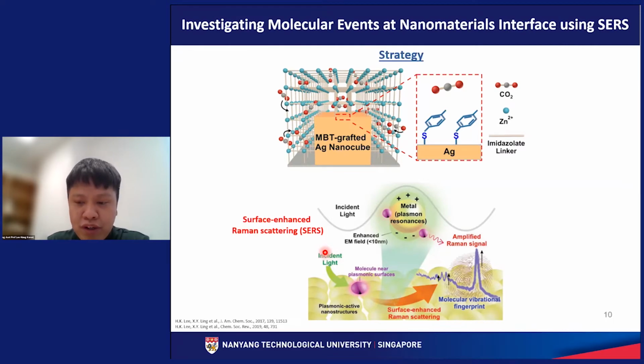Okay, one point to note is that for SERS, it is a very surface sensitive technique whereby we are trying to probe the molecular environment that is within 10 nanometer range from the particle surface. So in short, we are able to probe what exactly is happening on the particle surface. This is important for us to understand the rationale behind the reduced activation energy in core shell structure.